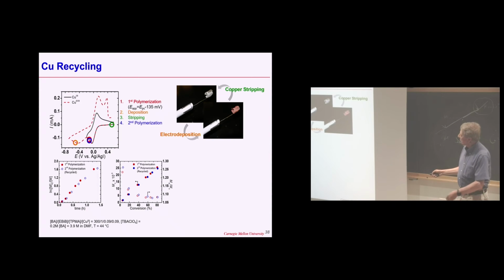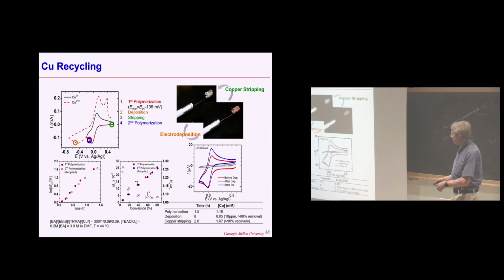And if I go to the original potential, I have the same rate of polymerization, same molecular weight, same dispersity, and you can remove maybe 98% of copper this way and strip it back probably with over 90% efficiency. So this is a very unusual way that by changing potential, you can also stop the reaction, restart the reaction, and remove copper, which would be important for some applications.